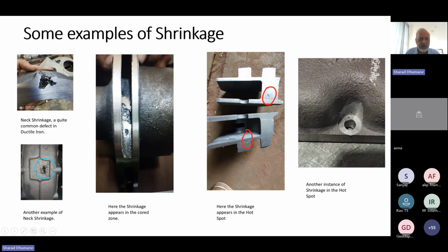You can see the appearance of shrinkage defects are different. Here it is a big defect, whereas here these are only small pinhole sort of defects. Another very common defect is when we make drills. We drill and then inside we find porosity, very small defect. So you can see defect here, and also inside the bore there is a defect. So these are the shrinkage images, and they differ quite a lot. So it is important that we identify the defect correctly. Most of the times, the location of the defect helps us identify it correctly. But if we don't, in some cases, a slag defect can also appear like a shrinkage defect.